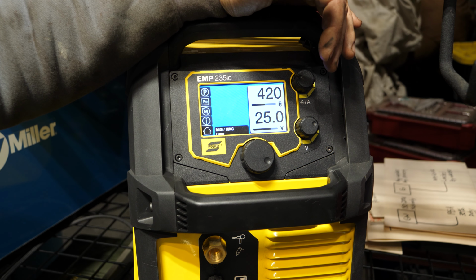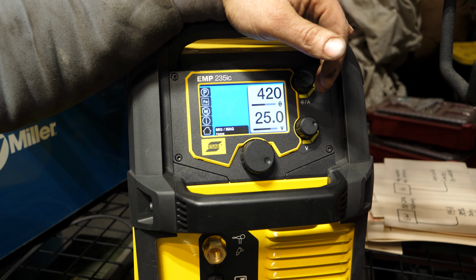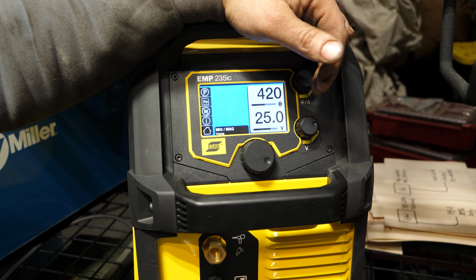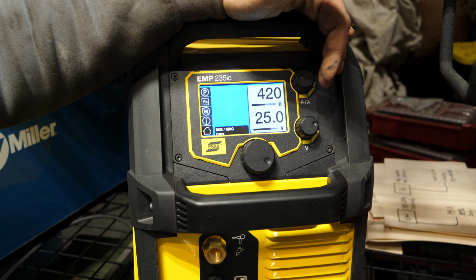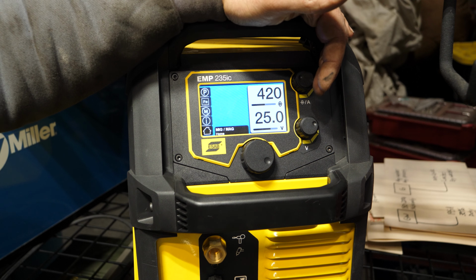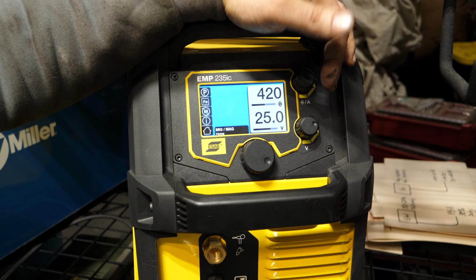You still need some pretty heavy duty contact tips, and you generally will run a little bit longer stick out with spray to get a little bit longer longevity out of that contact tip over your short circuit MIG.